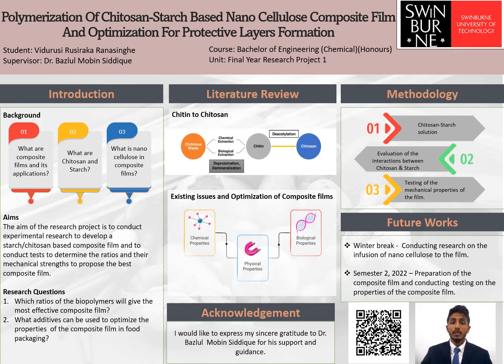Another similar issue is caused by films that lack strength, which cannot withstand high temperatures, water permeability, gas permeability, and even physical damage. So in order to overcome this problem, plasticizers are added to provide the necessary workability to biopolymers. Plasticizers are an important class of low molecular weight non-volatile compounds that are widely used in polymer industries as additives. These substances reduce the tension of deformation, density, viscosity, and electrostatic charge of a polymer, at the same time as increasing the polymer chain flexibility and resistance to fracture of the film.